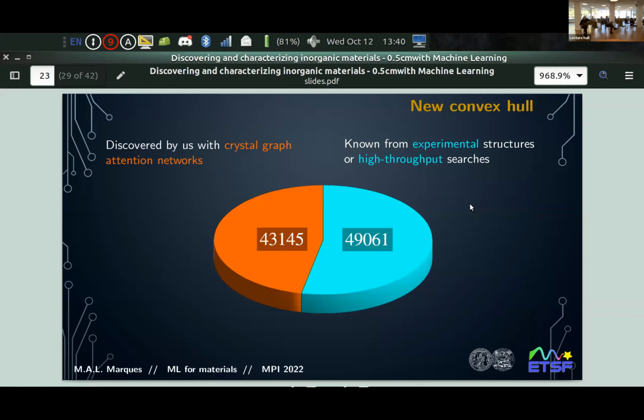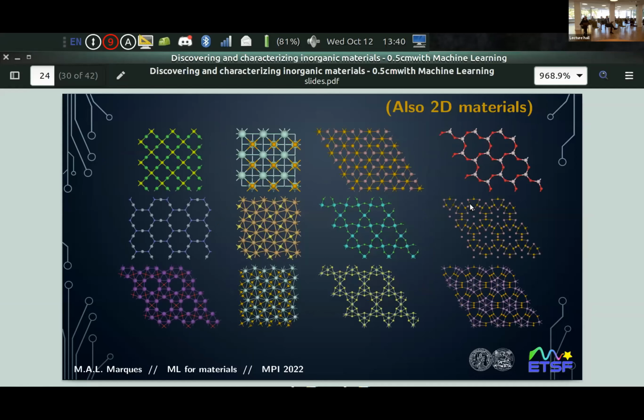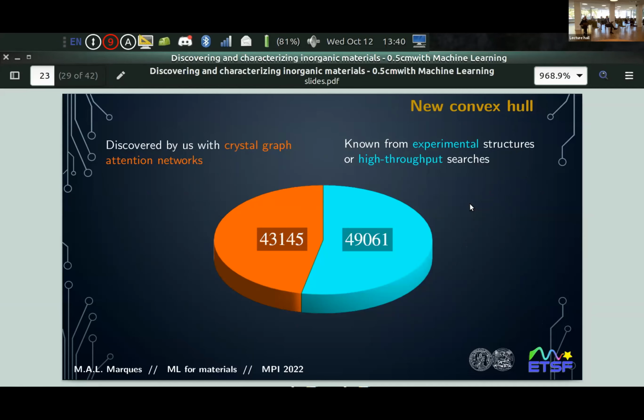Predictions. And so within that, there must be the 50,000 known inorganic compounds. So you predict all the known compounds. How many of the known compounds are in that? The known compounds here are less than 50,000, because 50,000 includes more than one stable phase. On the whole, I think there are a bit less than 30,000 from experimentally known compounds.